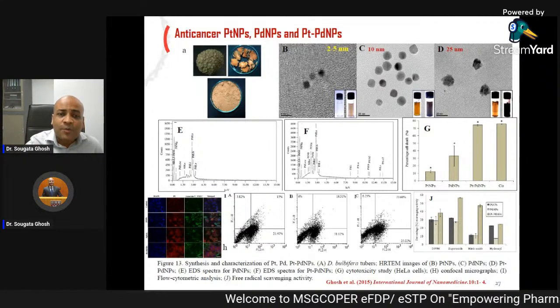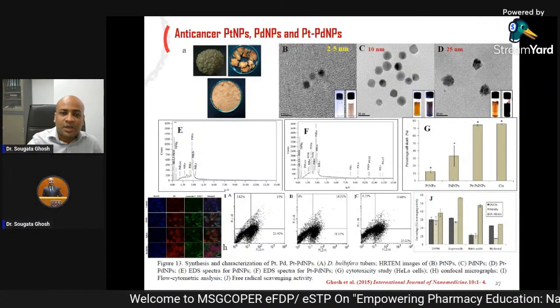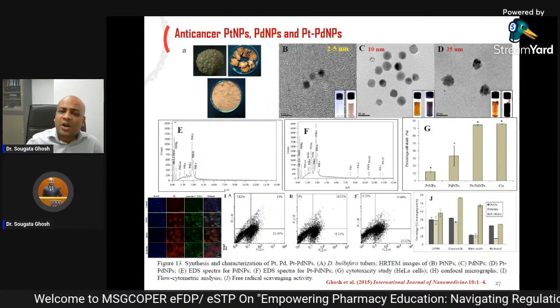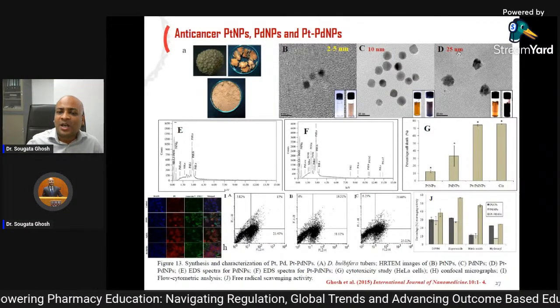The smaller the nanoparticle, the better the activity. It could produce palladium nanoparticles, which were 10 nanometers. It could produce platinum palladium bimetallic nanoparticles, which were 25 nanometers. So these are very, very small nanoparticles.